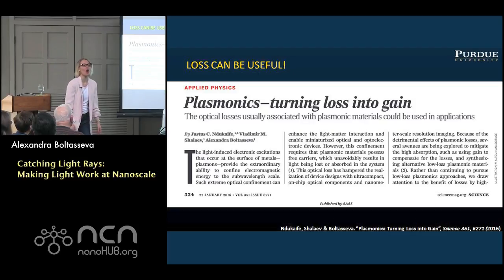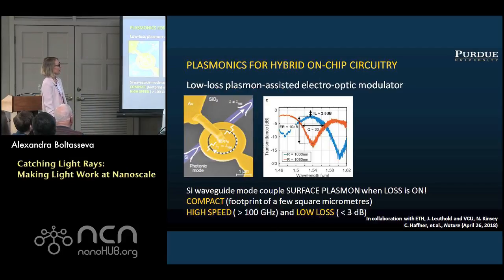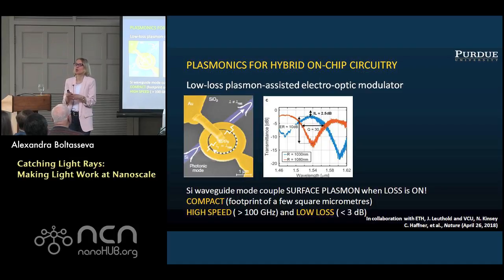And one of the demonstrations of how we want to do that is going to appear in Nature in 2 days, April 26th. And Kayla is right here with a press release. And I said, is it okay to talk about it? So probably it's okay. You're not going to shout after the seminar that this is what they did. But what we really showed is that you can indeed use the best of two different worlds. You can propagate your light using transparent materials so that we are not limited by absorption or loss in metals, but you can still have metallic or plasmonic components on top of your waveguide such that when you want to switch your signal off, it couples to this metallic mode. So what we call a plasmon-assisted electro-optic modulator would be an essential piece in a circuitry.